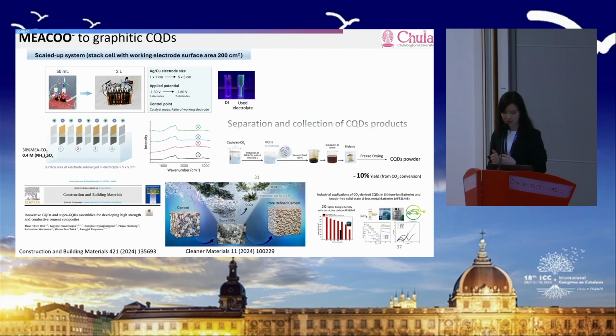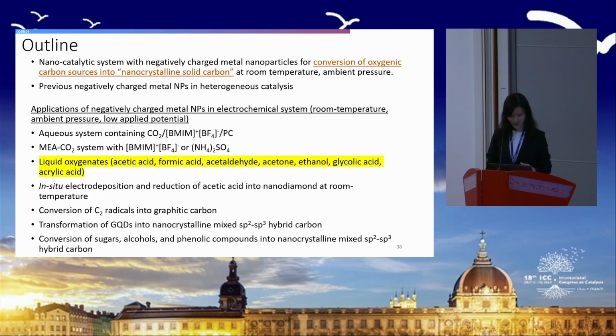And the amount of carbon, if you ask me the yield, it's about 10% yield, not so much, but that's really from carbon dioxide, you know. So we got 10% yield from the first cycle, I think, of carbon quantum dots, and then separate them out. And I already applied them. They already found applications, like you can put just a little bit to enhance the strength as a cement concrete strength enhancer. We can use them in batteries. I already applied them in different types of applications. So if you're interested in my CO2-derived carbon, you can just contact me.